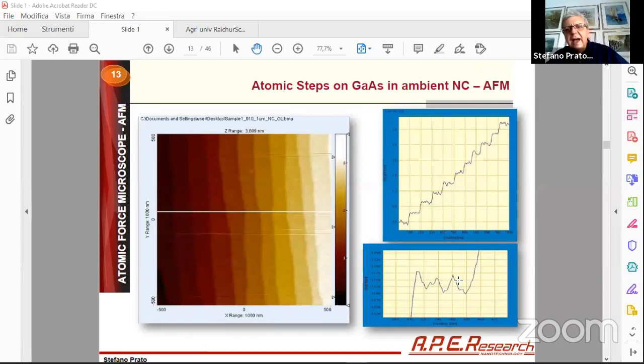This is the kind of resolution that an AFM, in particular our AFM, I would say, not all the AFMs can achieve. But this is the Z resolution that we can achieve. That is quite amazing if you think also of some other techniques. Okay, it's clear that even with the TEM, you can have a very nice lateral resolution, but the Z resolution is not as good as the AFM.